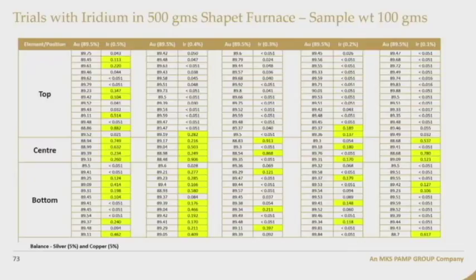What we did is we melted 100 grams of gold alloy after adding iridium 0.1, 0.2, 0.3, 0.4, 0.5% and melted it in a 500 gram furnace. We highlighted in yellow wherever we found iridium presence of more than 0.1%. So you see, there is more probability of finding iridium at the bottom portion or the center portion.